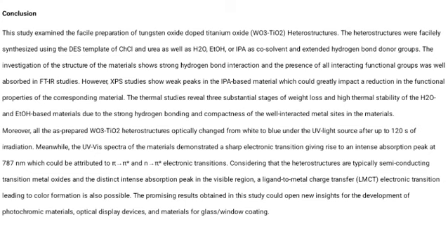In conclusion, this study examined the facile preparation of tungsten oxide doped titanium oxide heterostructures, and these heterostructures were facilely synthesized using deep eutectic solvent templates of choline chloride and urea, as well as water, ethanol, and isopropyl alcohol as co-solvents for the extended hydrogen bond donor. The investigation of the structures of the material shows strong hydrogen bond interaction and the presence of all interacting functional groups, as was well observed in FTIR studies.